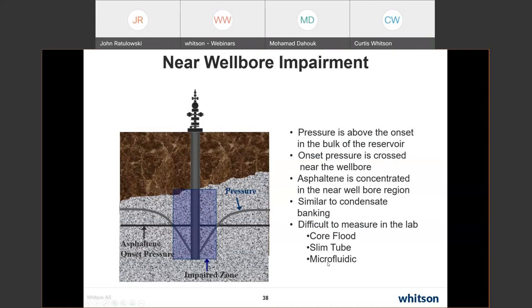It's really difficult to measure this in the lab because this is all high temperature, high pressure. And there are some issues with core floods or slim tube: you do need to actually hit the asphaltene onset in the porous media because it will make a difference. If you hit it outside of the porous media, you tend to just filter the stuff off at the face of the porous media you're injecting into. So we have done some core floods. There's a nice slim tube experiment that was done. Maybe some microfluidic measurements can also help us better understand this process.